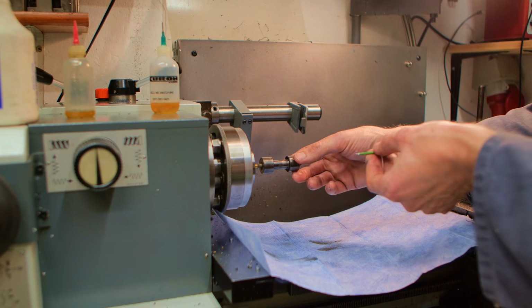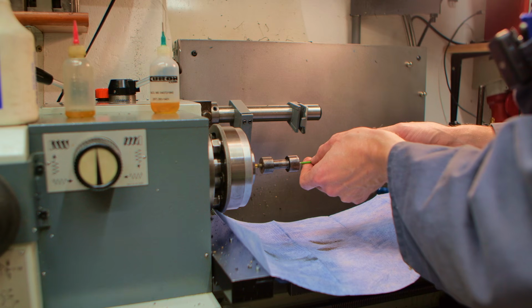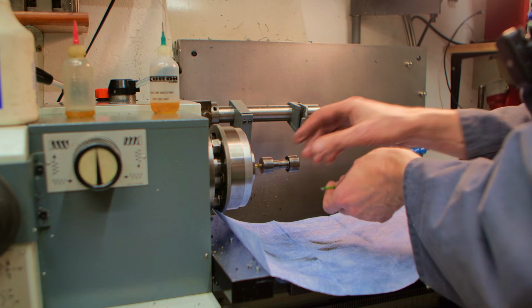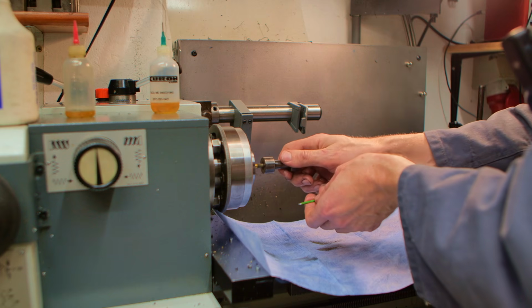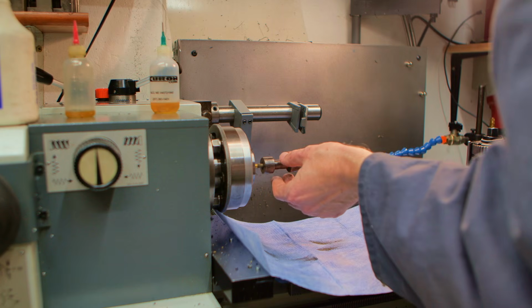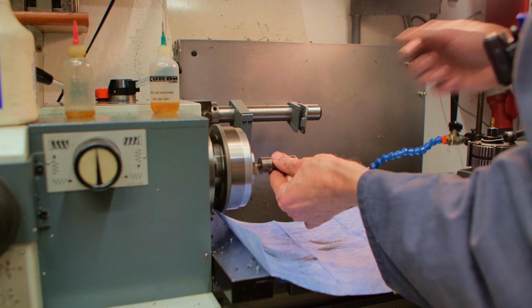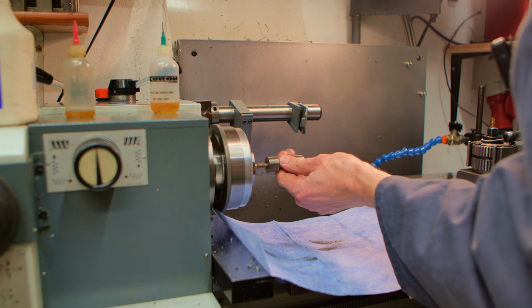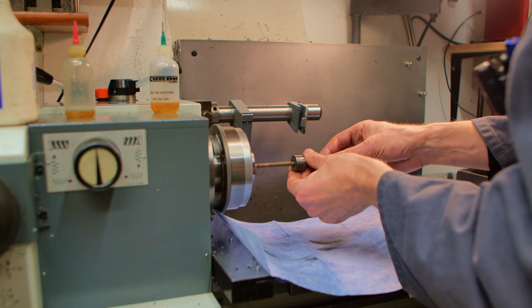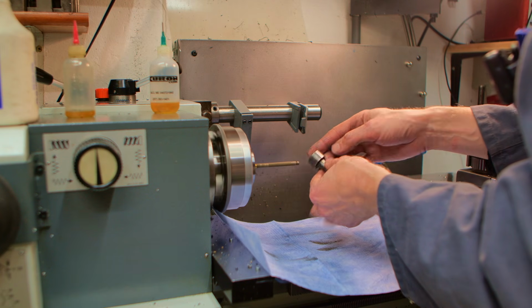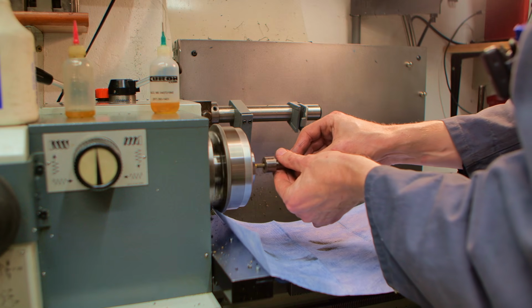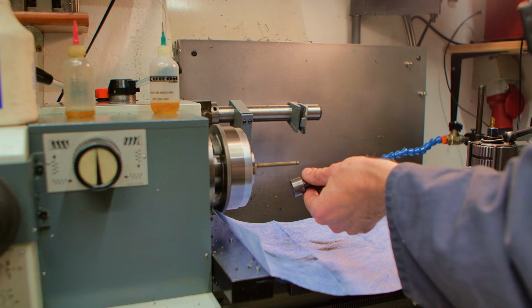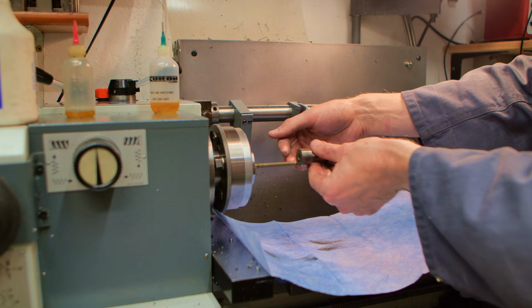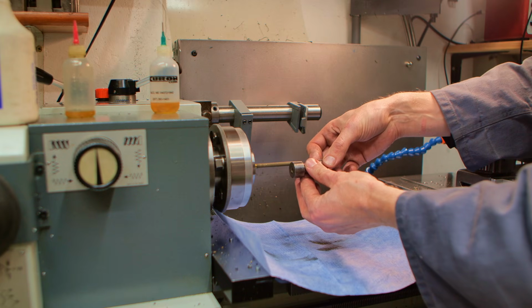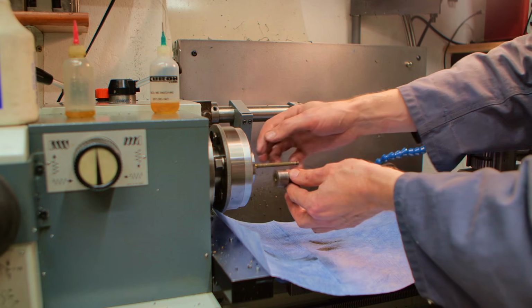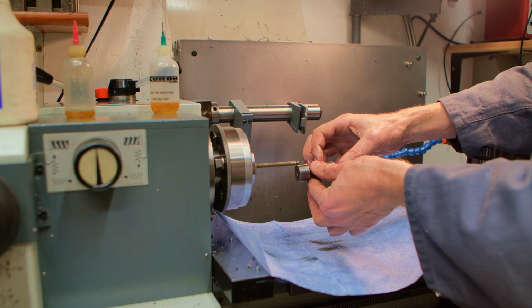At some point you notice that the part moves very free on the lap, then it's time to adjust the preload a little bit. And you're kind of using the lap like a gauge, depending on the force you need to hold the part to prevent the part from spinning with the lap. That tells you very precisely where you need to move your part and where to remove material.